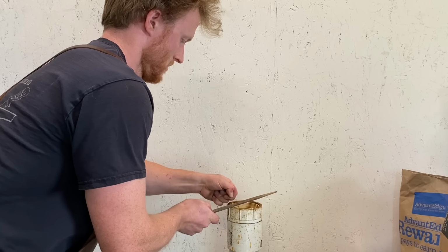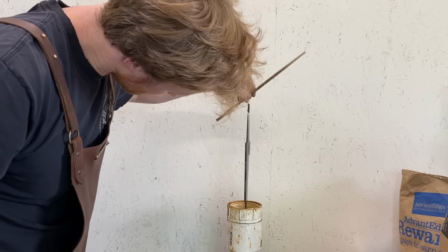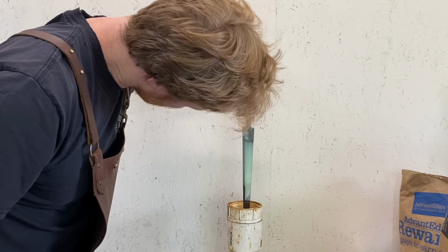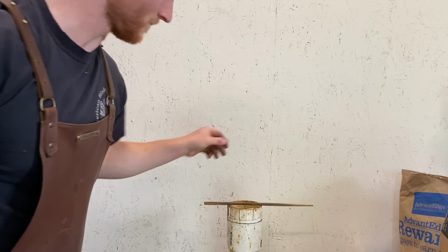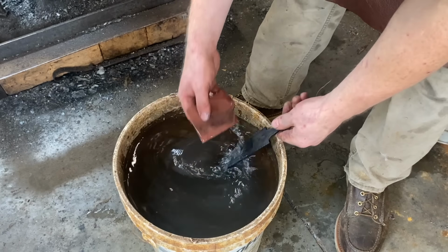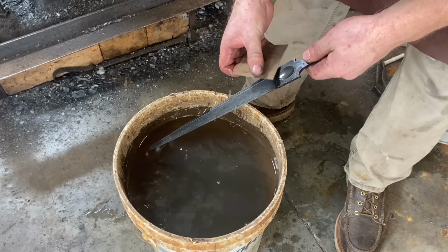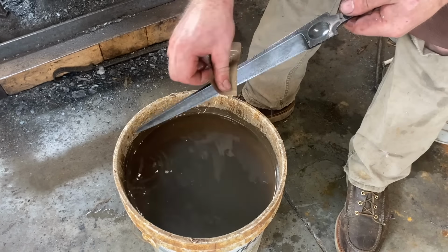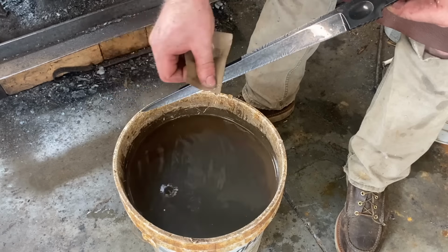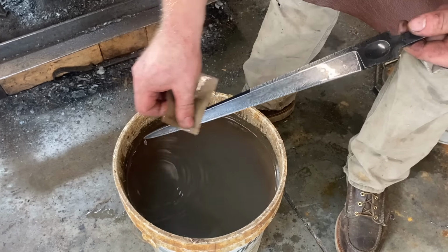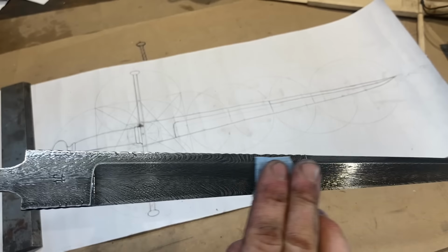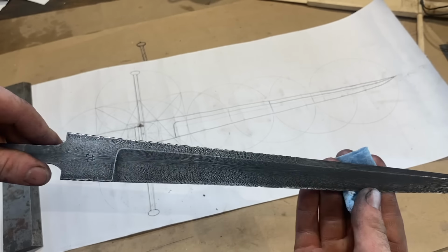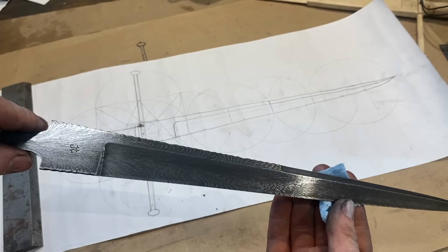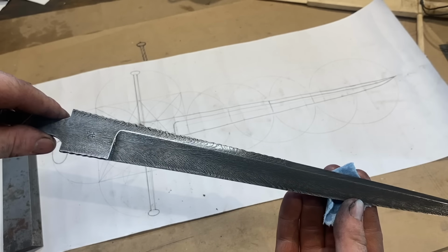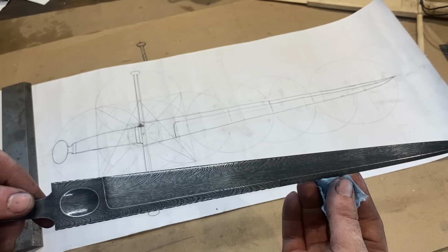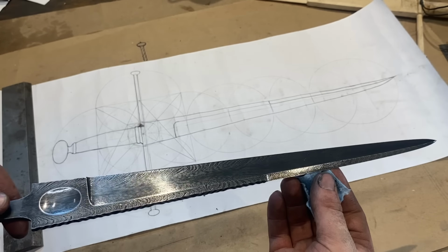I etched the blade in a ferric chloride solution, which reacts differently with the two different steels, so the 15N20 stays shiny and the 80CRV2 darkens. After a while in the acid, then I'll take it off and clean it with a high grit sandpaper. Once the etch is deep enough, then I'll neutralize the blade, dry it off, and oil it. So here I have the finally etched blade, and it's now ready for guard and handle.